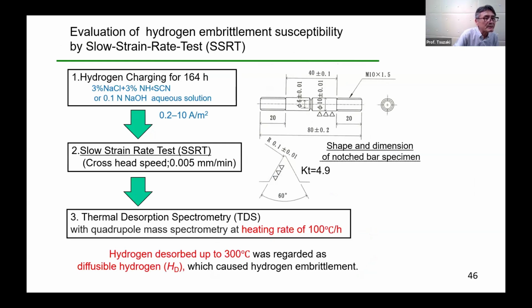The temp-forming process is exactly the same as that of the first half of my presentation today. This is the experimental method used to evaluate the hydrogen embrittlement susceptibility. It is the SSRT we always use. First, hydrogen charging for 164 hours with these solutions with various current density. Second, a slow strain rate test was performed at a cross-head speed of 0.005 millimeter per minute. Finally, we did thermal desorption spectrometry, TDS, at a heating rate of 100 degrees Celsius per hour. Hydrogen desorbed up to 300 degrees Celsius was regarded as diffusible hydrogen, HD, which caused hydrogen embrittlement.